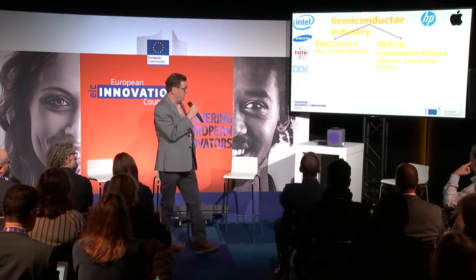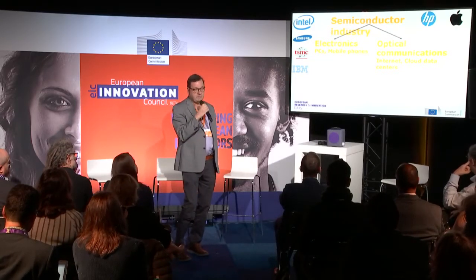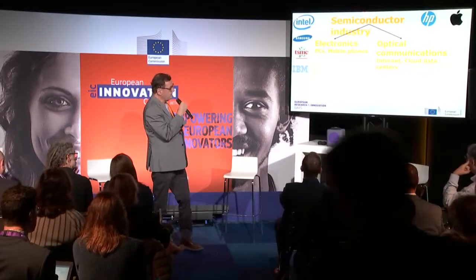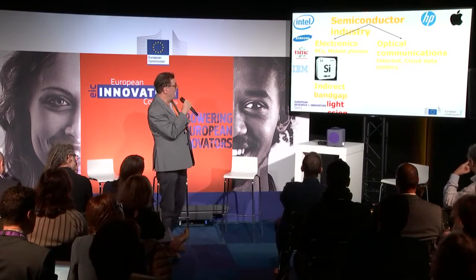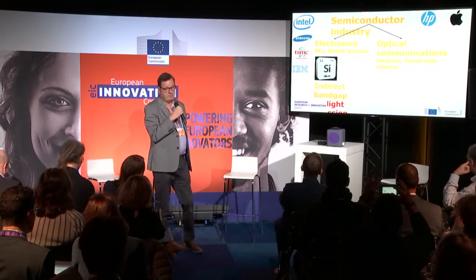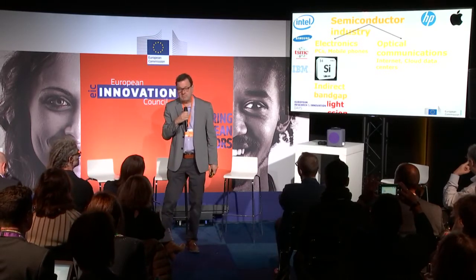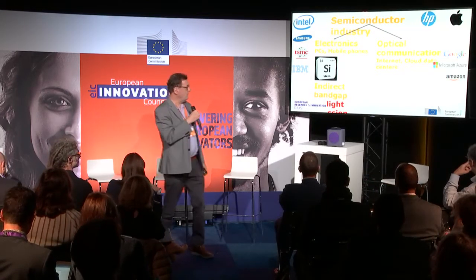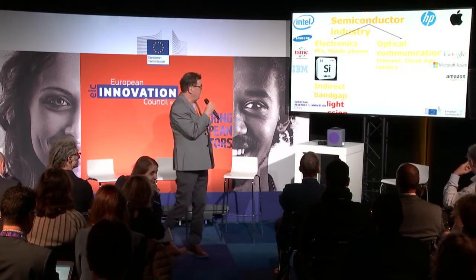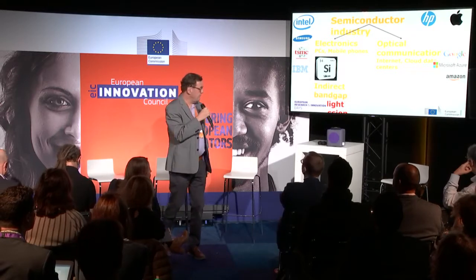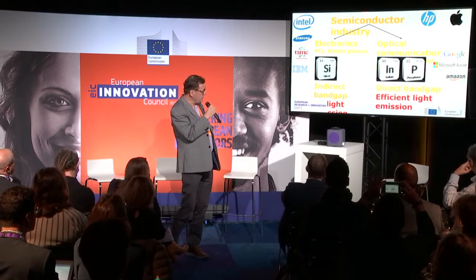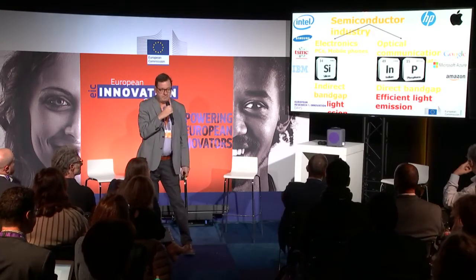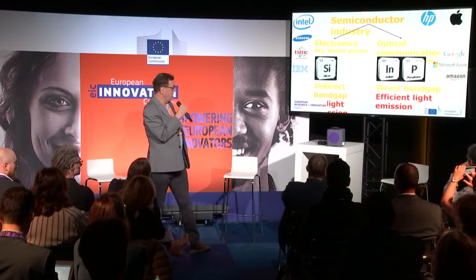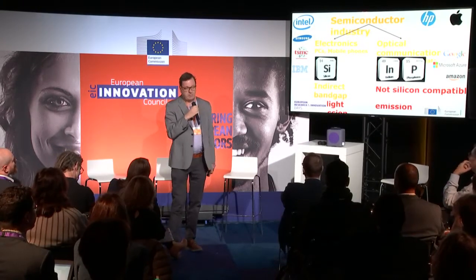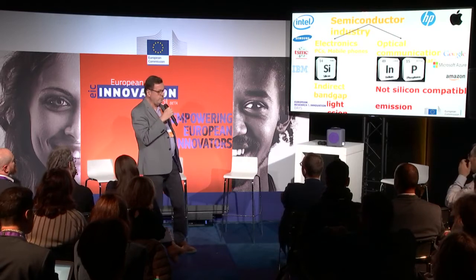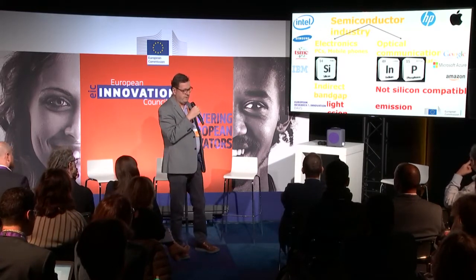So let's look at the semiconductor industry. Currently, the semiconductor industry is subdivided into the electronics industry and the optical communications industry. And if you look at the electronics industry, then the workhorse is really silicon. But silicon has an indirect band gap, so it can never emit any light. On the other hand, you have a growing optical communication industry with the internet, with all kinds of cloud data centers. And here the workhorse is indium phosphide. Indium phosphide is a direct band gap semiconductor which efficiently emits light. Now the problem with indium phosphide is that it's not silicon compatible. So there is not a scalable fabrication route towards fabricating indium phosphide on silicon devices. And that's a big problem.